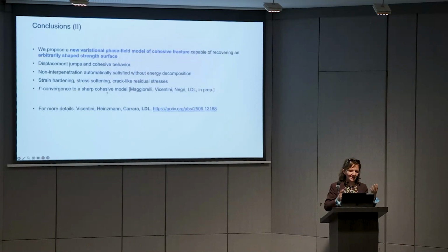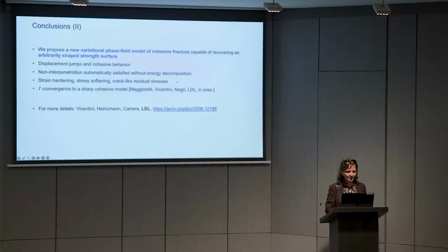But finally, we are still actually at the beginning of this new journey. So I think this new class of models will really enable us to make one step forward. It enables us to recover an arbitrarily shaped strength surface. It has displacement jumps and a cohesive behavior. We satisfy automatically non-interpenetration, so we don't need any energy decomposition because interpenetration is accounted for at the outset. We satisfy a priori stress softening and crack-like residual stresses.